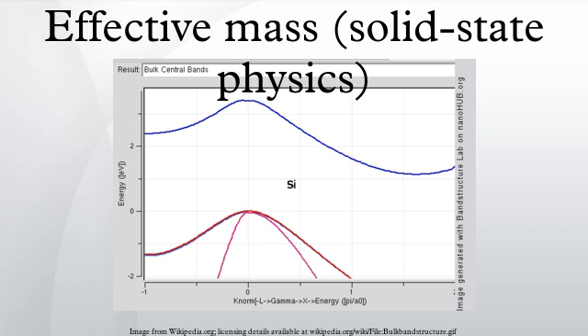This is a consequence of Fermi-Dirac statistics limiting towards Maxwell-Boltzmann statistics. The concept of effective mass is useful to model the temperature dependence of NC, thereby allowing the above relationship to be used over a range of temperatures. In an idealized three-dimensional material with a parabolic band, the concentration coefficient is given by... In semiconductors with non-simple band structures, this relationship is used to define an effective mass, known as the density of states effective mass of electrons. The name density of states effective mass is used since the above expression for NC is derived via the density of states for a parabolic band.